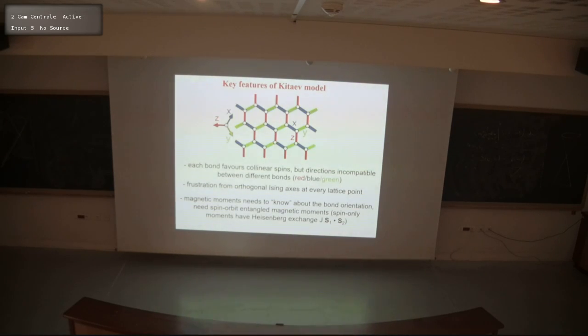And just the very fact that we need strongly anisotropic interactions, as Lucille explained in her talk, means that spin-orbit coupling is essential. Because any anisotropy is a combined effect of crystal field interactions and spin-orbit coupling. Spins by themselves don't know about the lattice. It's only their orbital motion that samples the bond environment, and only that way, through the spin-orbit coupling, they can acquire knowledge about the lattice environment, so an anisotropy direction.